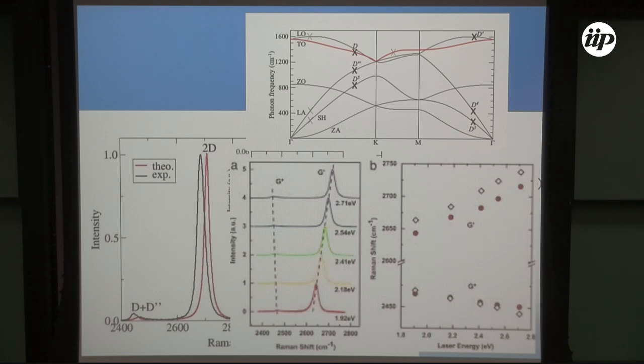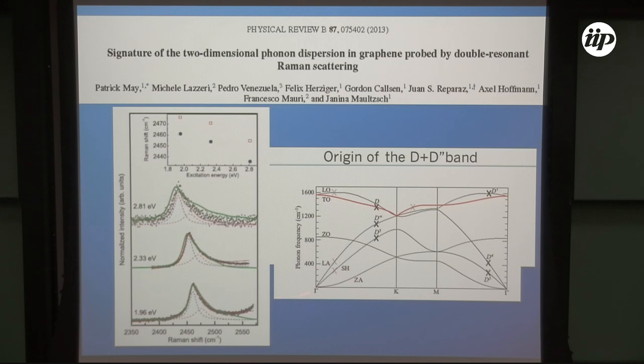By the time we did this work, there was a PRL by Daniela Mafra, who at the time was a student in Mildred Dresselhaus' group at MIT, and they wrote a PRL saying that this peak is due to two sub-peaks, and one of these sub-peaks was non-dispersive, in the sense that it does not change frequency when you change laser energy. So they claimed that one of the sub-peaks here was due to two phonons exactly at the K point. And if you look at momentum and energy conservation, that would be possible. You could have a peak from two phonons here that would explain this.